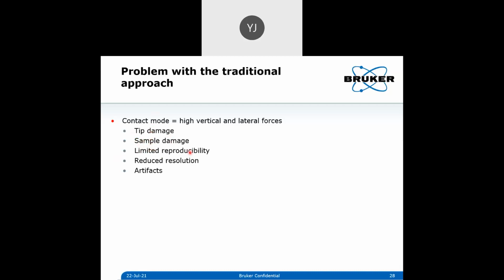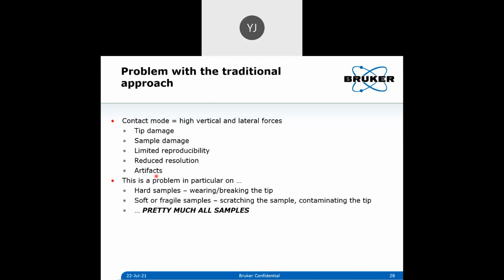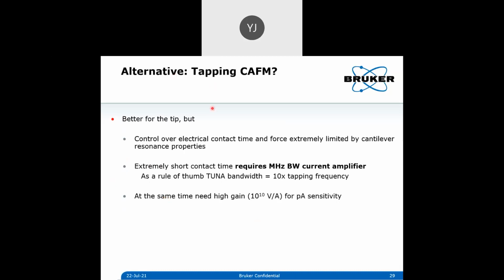And because of these two, you have a problem of reproducibility, and sometimes reduced resolution, and some artifacts created by that, right? So pretty much all samples have some problem or other when doing conductive AFM. And why can't we do tapping mode conductive AFM? People are unable to achieve that because you are oscillating your cantilever close to the resonance frequency, right? And that means you do not have control of the contact time. It's very, very short. You might need a very high bandwidth amplifier with very high sensitivity, which is not really feasible at the moment.